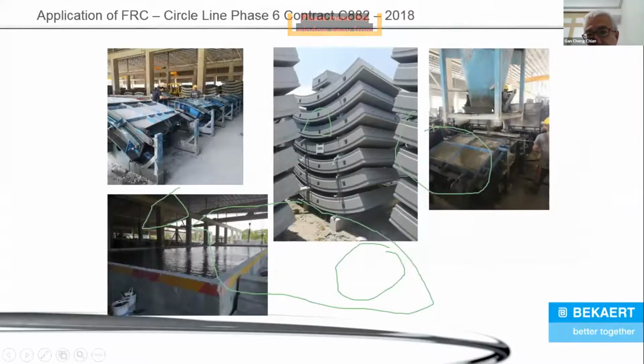And on the right-hand side, you see the bucket pouring fiber concrete into the mold. And on the left, these are the molds. And these are the completed segments, 7+1. So 8 segments are stacked together, and there is no problem with the loads. And over here, you see a big swimming pool. This is the curing pool for the segments. So segments are cured inside a swimming pool. It's water cured.